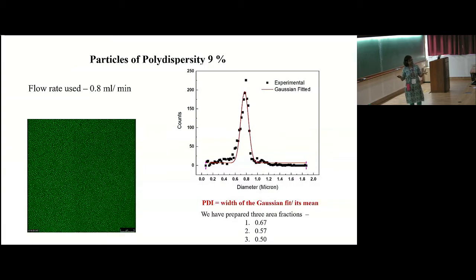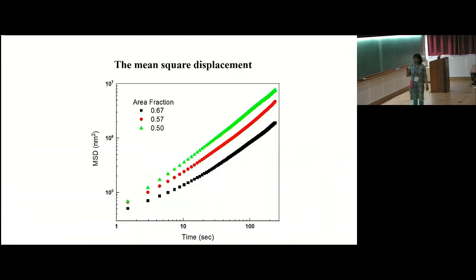And we took these particles, we diluted it, and then we got a particular area fraction. We diluted it a bit more twice, and then we got three different area fractions. We track the particles, we track the center of mass over several frames. And then we've averaged over all the different particles in the frame. So this is the mean square displacement versus time for three different area fractions. And you can see for the highest area fraction here, there is a weak caging behavior which breaks up at larger times, as well as when you dilute the suspension. So there's a fluidization of the suspension at lower area fractions.